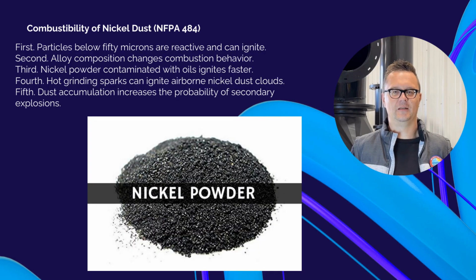Combustibility of nickel dust, NFPA 484. Nickel dust is less explosive than magnesium or aluminum, but still regulated by NFPA 484 because first, particles below 50 microns are reactive and can ignite. Second, alloy composition changes combustion behavior. Third, nickel powder contaminated with oils ignites faster. Fourth, hot grinding sparks can ignite airborne nickel dust clouds. Fifth, dust accumulation increases the probability of secondary explosions. If it is fine, airborne, and metallic, it must follow NFPA 484.